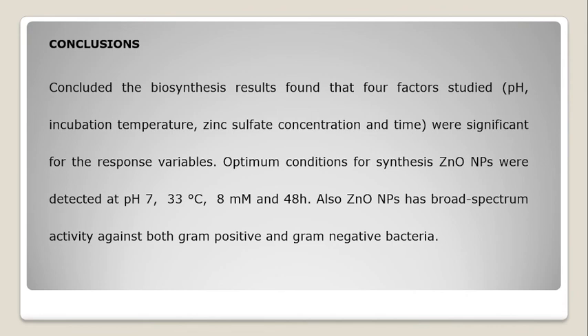Conclusions. The biosynthesis results found that the 4 factors studied, like pH, temperature, etc., were significant for the response variables. The optimum conditions for synthesis of zinc oxide nanoparticles were detected at pH 7, 33 centigrade, 8 millimole, and 48 hours. Also, zinc oxide nanoparticles have broad spectrum activity against both gram-positive and gram-negative bacteria.